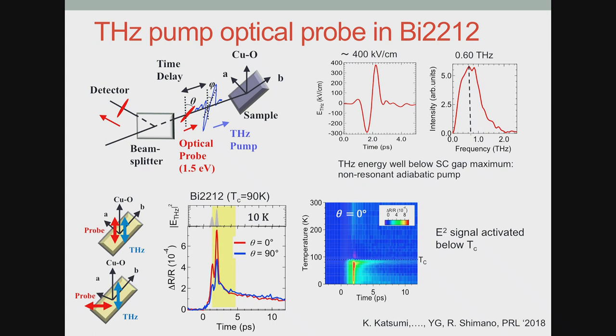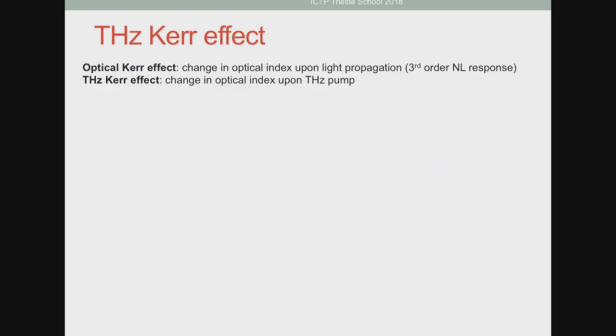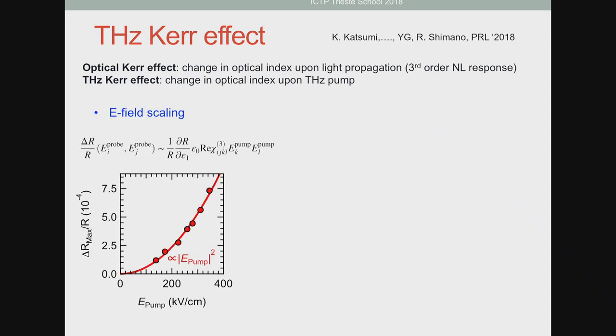And essentially, the effect that we are seeing here is a change in the optical index upon irradiating the sample via a terahertz electric field. So it's a change of optical index upon impacting it with a terahertz electric field. So this goes as E squared. So it should follow E squared scaling. And you see here that indeed it follows E squared of the pump.